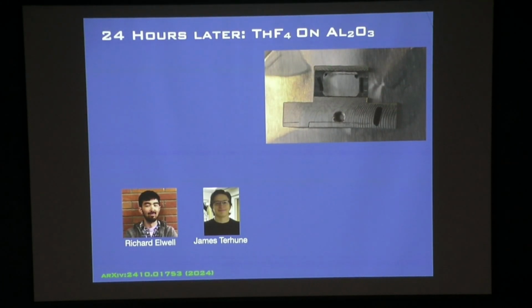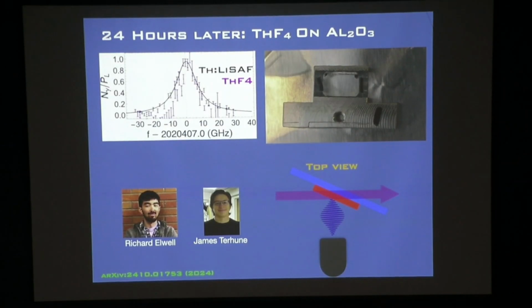Literally 24 hours later, we had it, and Ricky and James took the laser, put it through to collect fluorescence, and we saw this stupid transition in this thorium thin film, which honestly kind of made me mad a little bit, because this is just some crap sprayed onto a substrate. But when you take a step back, I think this is a really good sign for the field. We can see this even in crazy things.